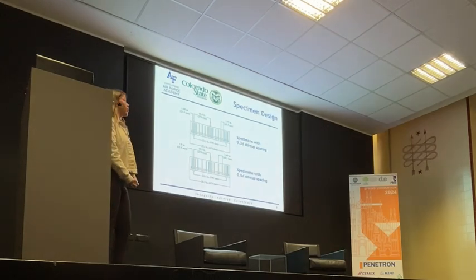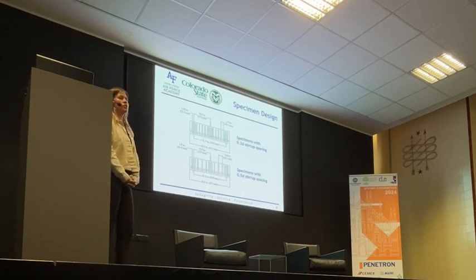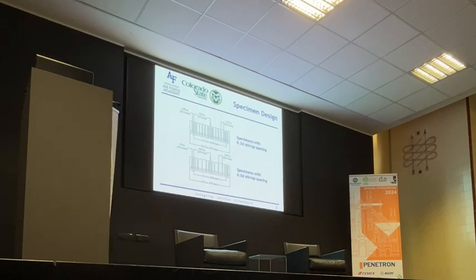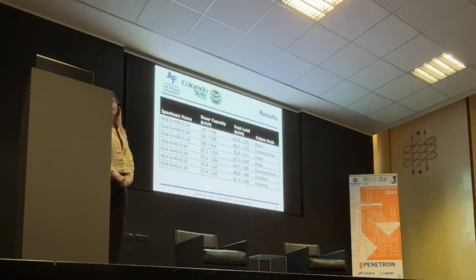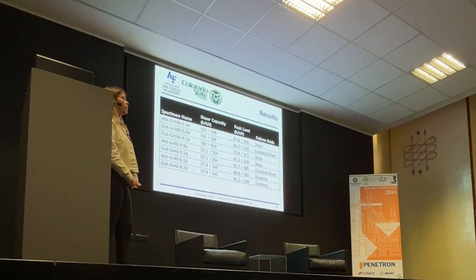So these are going to be the cross sections of our specimens, with the first 3 with the smaller transverse steel spacing on the top, and the 4 with the larger transverse steel spacing on the bottom. It's important to note here that our shear span to depth ratio was 2 for all 7 specimens. And then after curing, we conducted a 3-point loading test for all 7 specimens, with the results shown here.